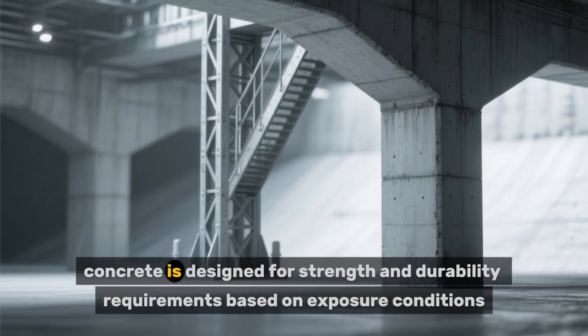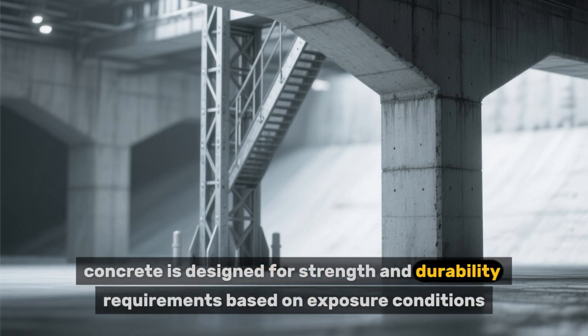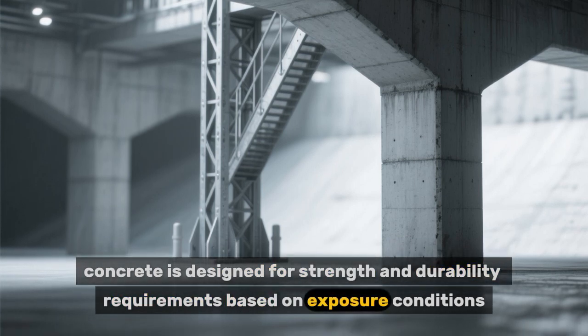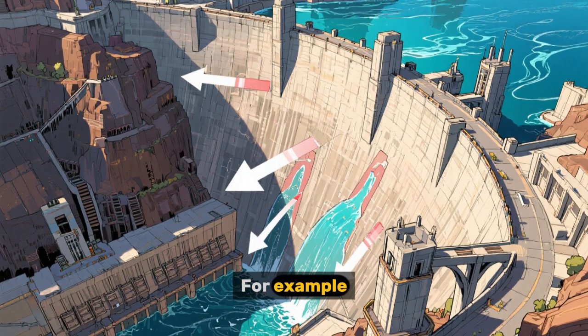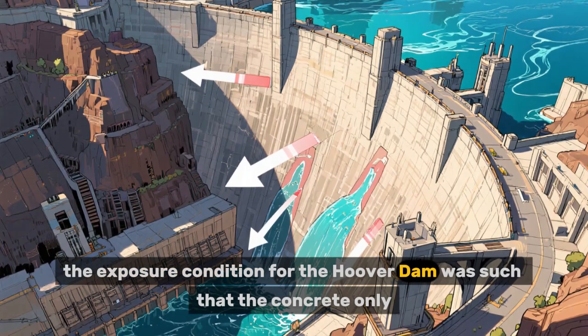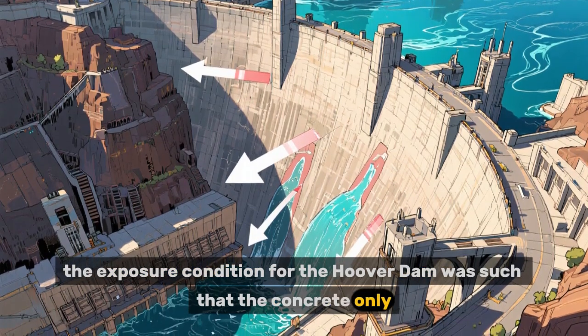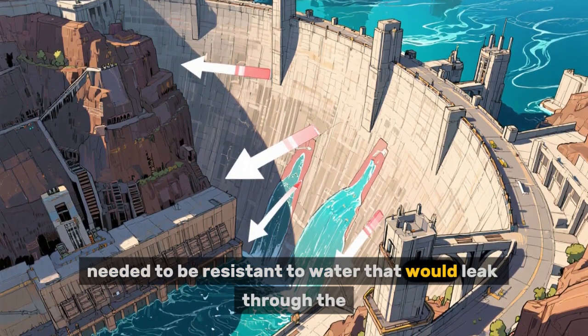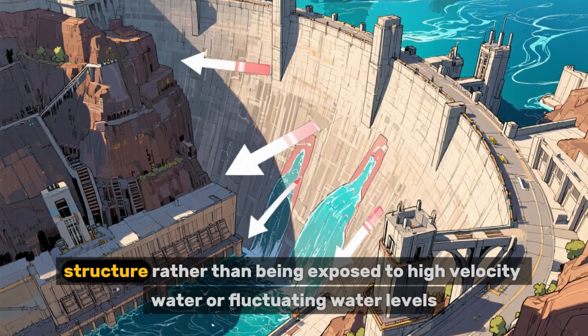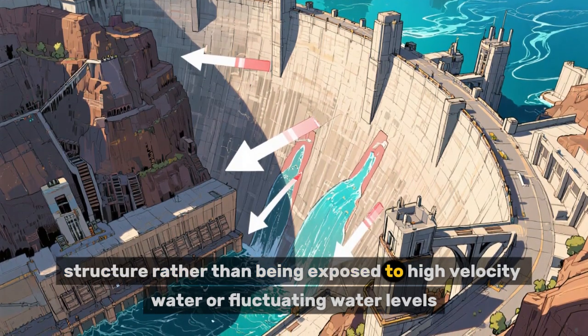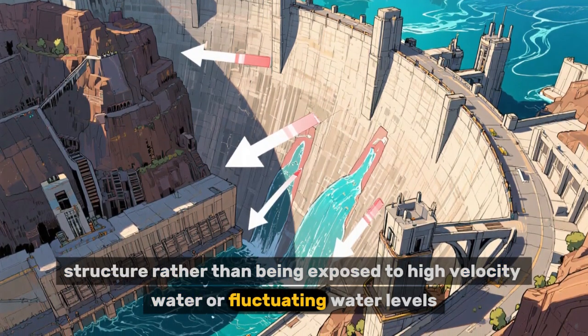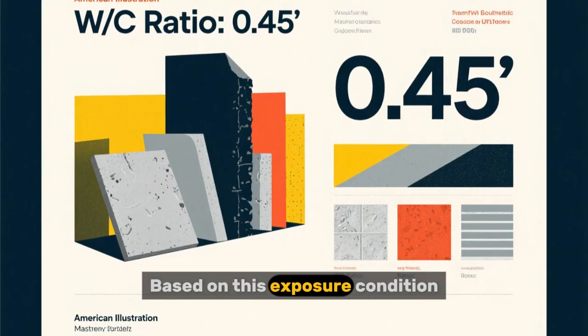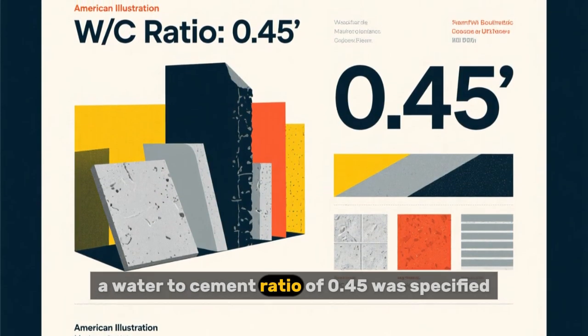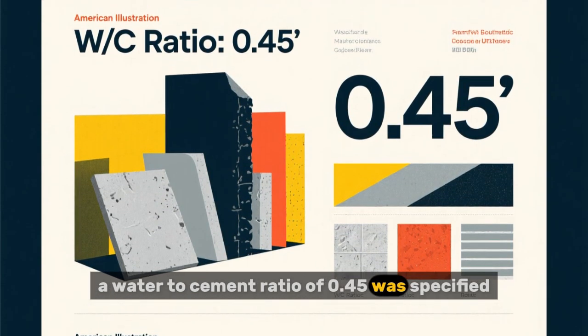Typically, concrete is designed for strength and durability requirements based on exposure conditions. For example, the exposure condition for the Hoover Dam was such that the concrete only needed to be resistant to water that would leak through the structure, rather than being exposed to high-velocity water or fluctuating water levels. Based on this exposure condition, a water-to-cement ratio of 0.45 was specified.